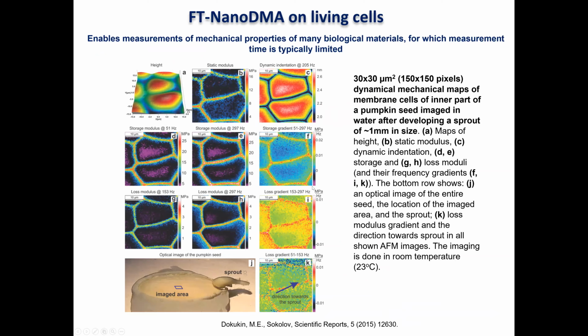So you can look at this picture I already showed you in the beginning. We can look at individual cells. Specifically here, the images were taken on a living sprout. Actually, there is a sprout developed here. It's a pumpkin seed, which was collected after Halloween. We had quite a lot of pumpkins around, and we simply planted one seed in a petri dish and added water, and it started growing. And then we simply looked at different surface areas, and we see clearly the structure of cells and different moduli recorded on it.